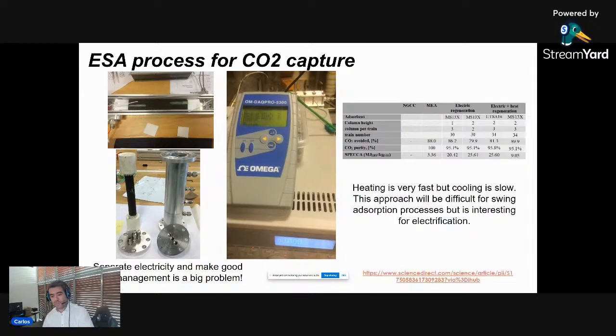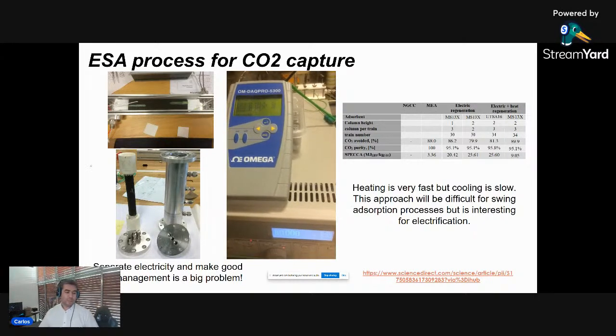So the adsorption goes really, really fast. The problem is that when you have so many measures to avoid, let's say, thermal expansion and gas bypasses, you are isolating this material so well that you cannot cool it down very properly. So you have to end up making a cycle to reduce the time for cooling down. And obviously the process becomes a bit inefficient, but you use a lot of energy. And also you have to take into account that this is, let's say, primary energy.